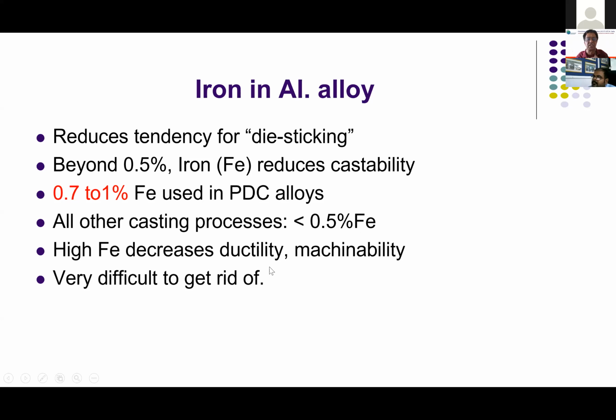High iron decreases the ductility and machinability. Machinability also gets reduced, and it is very difficult to get rid of. As I told you, you can only dilute it. You can't reduce iron. Once iron gets into the molten metal, casting, molten metal or in the casting, even on remelting, you can only dilute with a better metal with a low iron, so that total iron content comes down. It is very difficult to remove as such.